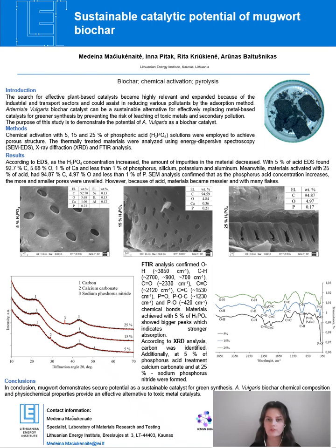So let's jump to the results, and first what I want to discuss is EDS results, and it showed that the more concentrated phosphoric acid was utilized, the fewer impurities in the materials formed. So in every sample, carbon was the one which occupied the biggest part of the materials, but additionally, with 5% of acid, calcium, phosphorus, silicon, potassium, and aluminum were noticed. Meanwhile, materials activated with 25% of acid were left only with carbon, oxygen, and just less than 1% of phosphorus.